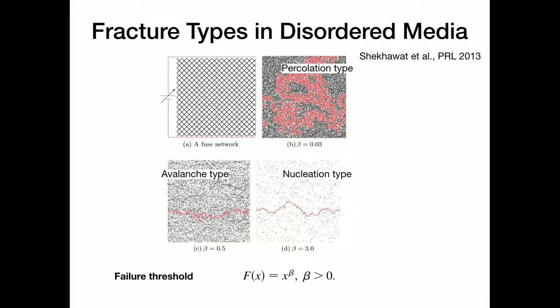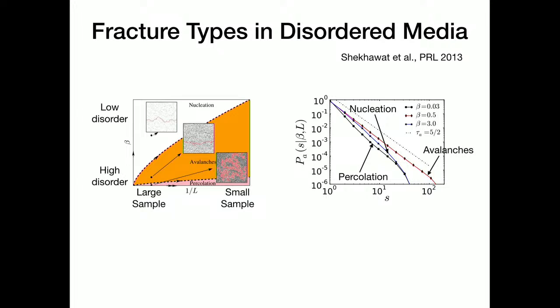So that avalanche power law behavior that was earlier said to be universal now has some conditions: it depends on the kind of disorder or the extent of disorder. Very high disorder has issues, very low disorder has issues. It's the intermediate range that we would look at. Based on that, this is the phase diagram in which, going from high disorder to low disorder, we go from percolation, avalanche type fracture to nucleation type fracture. But also, on this axis, for the same disorder, you could transition from avalanche type of behavior to nucleation type of behavior when the sample size is increased.